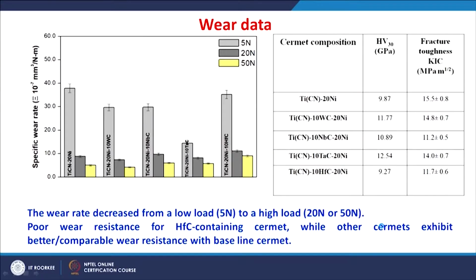Now, let us understand the wear behavior. The wear behavior can be understood by the specific wear rate data. Again, the surface profiles were recorded for each track at different locations, and then the depth and the width of the wear track were measured using stylus profilometry, and integrating over a distance, we get the volume of the material removal. It is normalized with the distance and the time, so we get a specific wear rate.